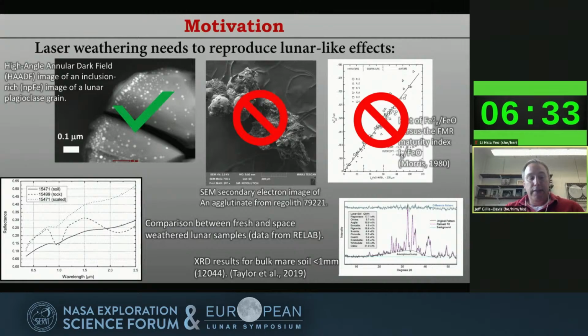And if we normalize that spectrum at 500 nanometers, at 0.5 microns, which is the line with the dots, you can see that the spectrum is also redder than the typical fresh rock material. In other words, it increases in reflectance as it increases in wavelength, and these are all key features in lunar space weathering. And the short pulse laser reproduces some of the darkening, definitely the reddening, and a little bit of the loss of the spectral absorption, but doesn't completely or nearly erase them like we see on the moon.